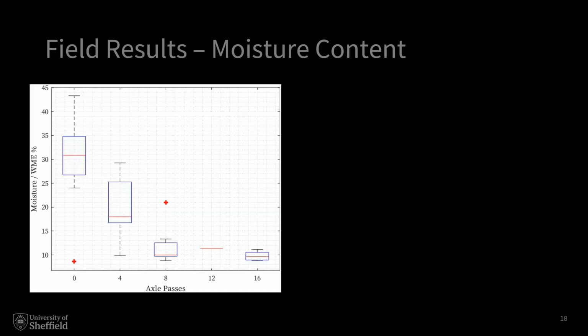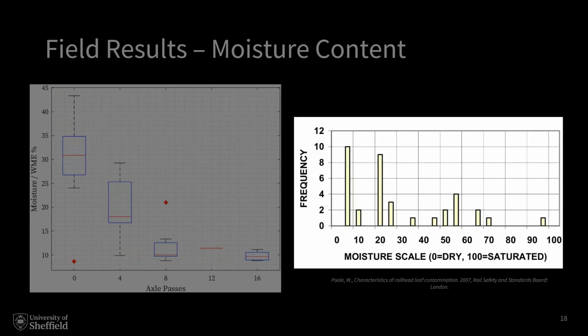We were also tracking the moisture content of the layers, and here you can see the results. This is what you'd expect in dry weather where there's no rain, no extra moisture being added from the environment. The layers start off quite wet, and then there's a significant drop, and then they seem to stay at quite a dried out level, and they maintain that level through repeated cycles.